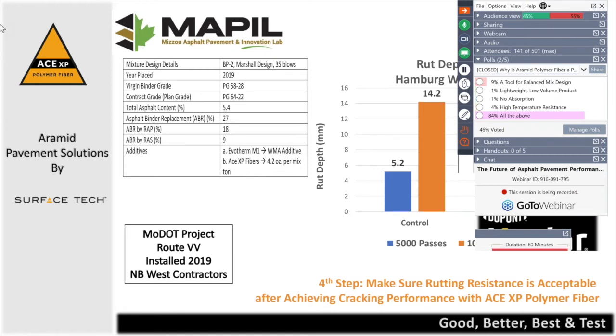So the next step in good, better, best is to know that once you've zeroed in on a better performing crack mix, you want to go back and rerun it in Hamburg and make sure that you haven't made it too soft to induce additional cracking or additional rutting. What we have found, because we're doing a lot of the modification with the fiber itself, is that we tend to improve cracking without giving much up in the way of rutting. And in a lot of cases, we improve that as well.